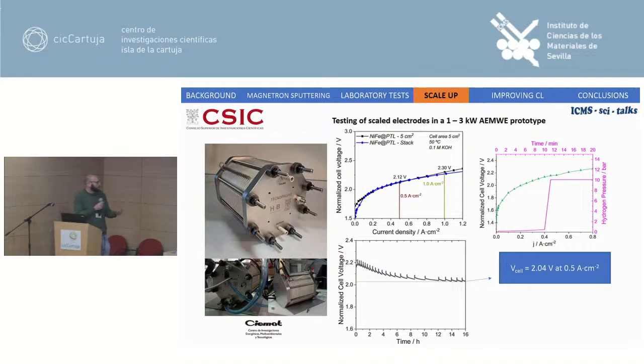So the final result is even much better than the original one in this polarization curve. As you can see here, we decreased the voltage from 2.12 volts to 2.04 volts. That means that the power density is less, so the hydrogen cost is also lower.